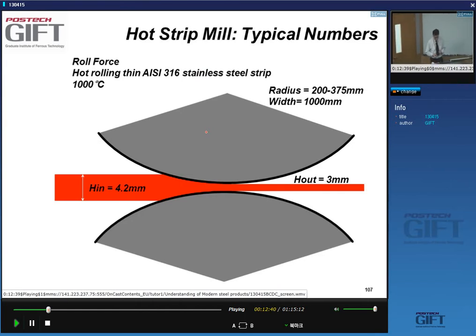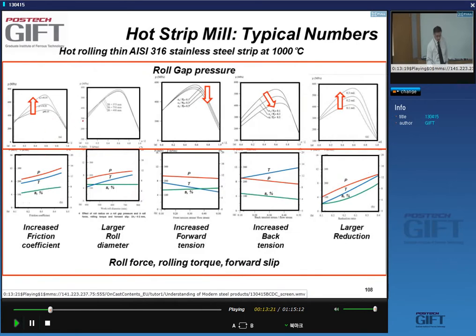Again, here are some typical numbers so you have a good physical feeling for what happens in a hot strip mill. For instance, here we're looking at some calculations for an austenitic stainless steel at 1,000 degrees C, and we're rolling with rolls of a radius of 200 to 400 millimeters. Strip widths are of the order of a meter or slightly smaller, often larger. And this would be a typical reduction: you go from 4 millimeters to 3 millimeters. And you can calculate